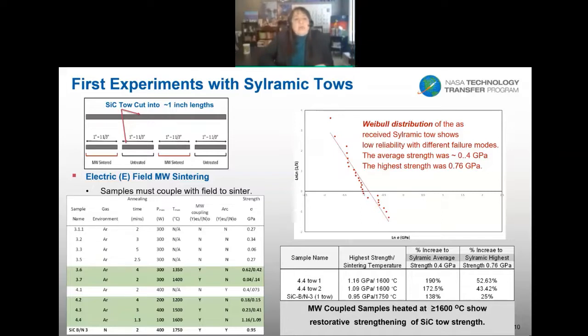We did see plasma quite a bit in the initial studies and arcing events, and we did have some studies where we actually maintained the arc. It's not like a steady arc like you might see in spark plasma sintering, but we did see an arc that was somewhat controlled up to 5 minutes, and we did see some strengths. But until I really get a chance to look at those and understand them, I didn't really want to report on that. For 1 minute, it looked pretty good, but when you got up to 5 minutes, it decreased. So arcing could also be a problem.